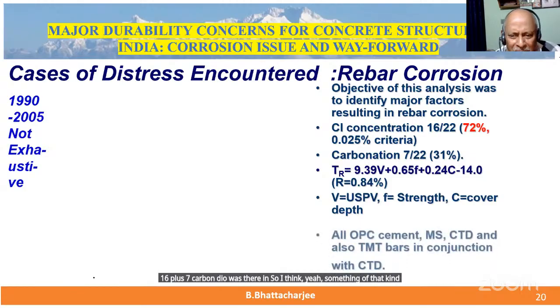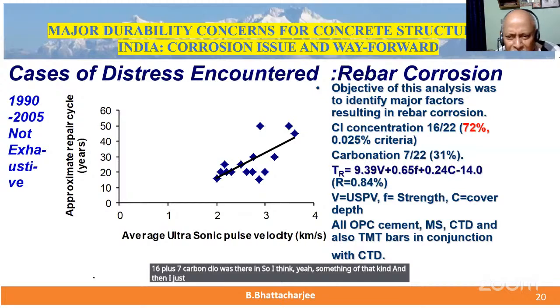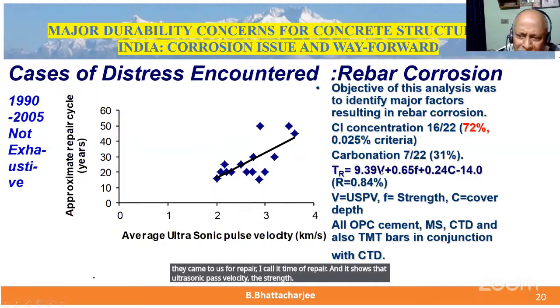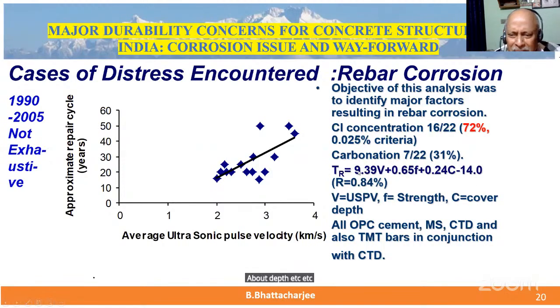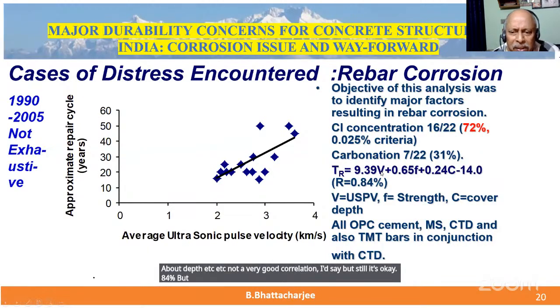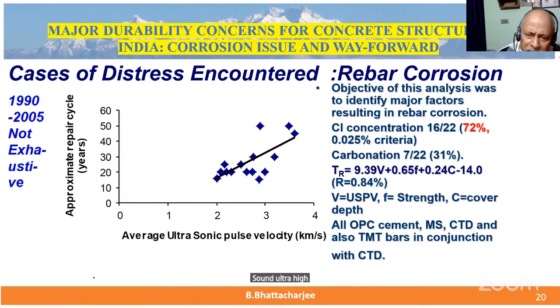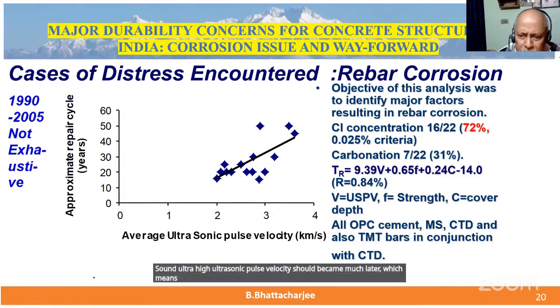And then I just thought to fit a multiple regression on the data, and the time at which they came to us for repair, I call it time of repair. It shows that ultrasonic pulse velocity, the strength, cover depth, etc., not a very good correlation, I'd say, but still it's okay, 84%. But this says the sound concrete tendency is better. Sound, high ultrasonic pulse velocity became much later, which means the quality control was better.